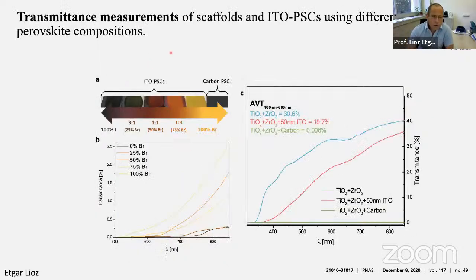As I said before, since we are using ITO, it has some transparency, and one of the motivations was that it can be used later on for a tandem structure. And here you can see, for example, a demonstration of different halide percentages in order to show you the transparency of the electrodes. For example, in the carbon cells, this cannot be done due to the complete darkness of the carbon.